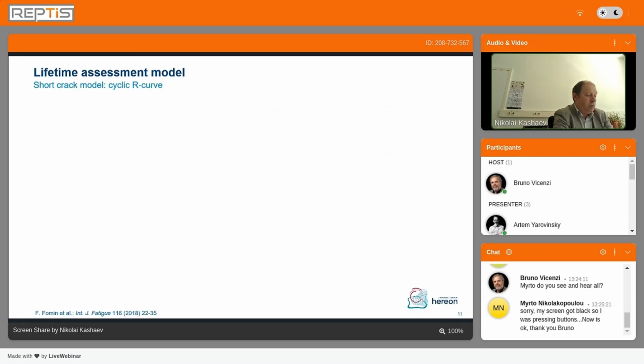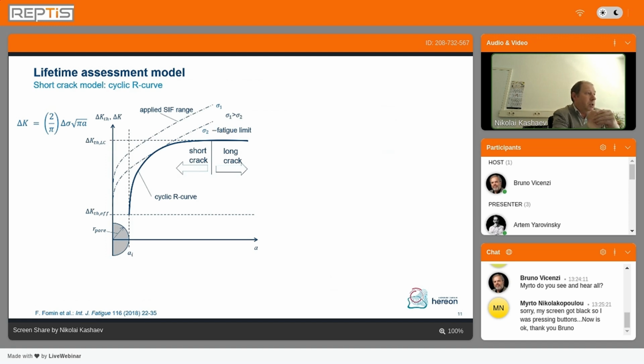First of all, with regard to the fatigue crack growth model, our assumption, which was successfully implemented, is to use the so-called cyclic R-curve. The cyclic R-curve describes, in principle, the near-threshold material behavior. It means we need to know the law of how the threshold of the material depends on the crack length. And if we go to fracture mechanics-based approaches, there are a number of ways to describe that kind of cyclic R-curve.